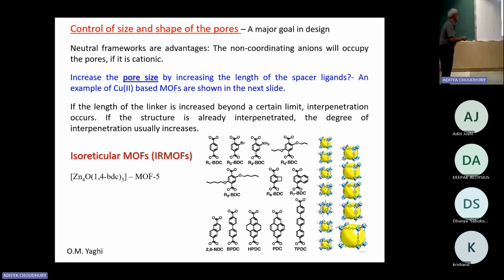How is it possible? It is possible because of the use of the cluster. If he had used one metal ion, it's not going to work. According to him, it's because of the cluster nature of the node that prevents interpenetration. That becomes really big. Secondly, he started using additional substitutions that also prevent further interpenetration, because if it has to interpenetrate, a similar type of ligand should go in, and he makes sure that's eliminated. So by using isoreticular MOFs, one can reduce interpenetration and control the size, or increase the size gradually.